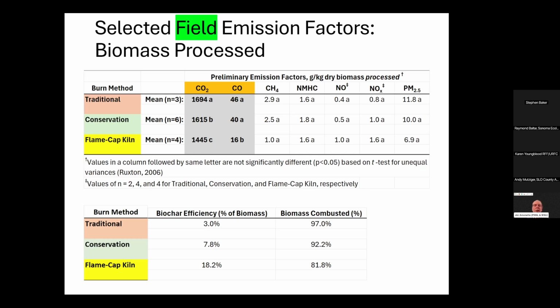So that makes a big difference, particularly when you're comparing the flame cap kiln with the other two, in that the emission factors are going to be quite a bit lower for the flame cap kiln because that was never emitted to begin with.